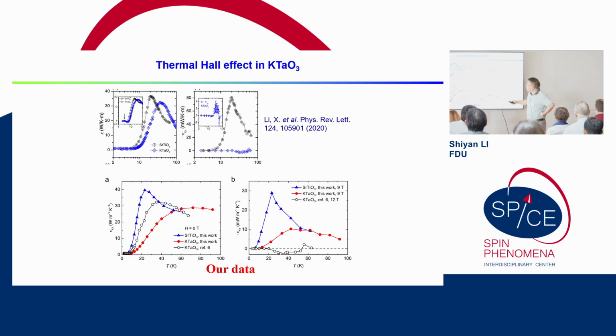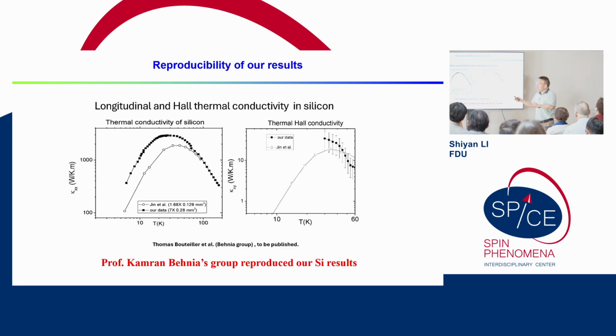Okay, then finally, all these trivial single crystals you can easily buy, and if you have a good experimental setup, you just need a few days to get the result. You can easily reproduce our result. Professor Behnia's group actually reproduced our results on silicon. They used quite a big sample, but I prefer a very thin sample.